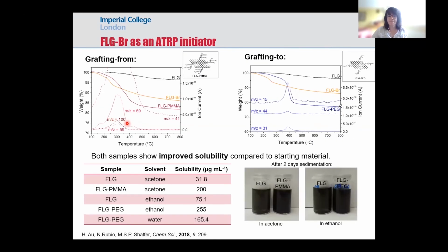So looking at the characterization using TGA, comparing the PMMA functionalized graphene and pegylated graphenes. This is the TGA of brominated graphene, and after carrying out the polymerization with PMMA, we observe an increase in the mass loss, meaning that we are introducing these PMMA chains, and confirmed also with the fragments from mass spectroscopy from the fragments of the polymer. And something similar we observe when we synthesize the pegylated graphenes. We observe an increase in the mass loss compared to the brominated ones, and with the fragments at 15 and 31 corresponding to the PEG chain.